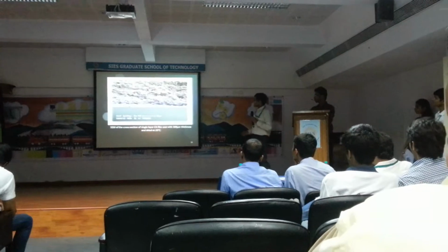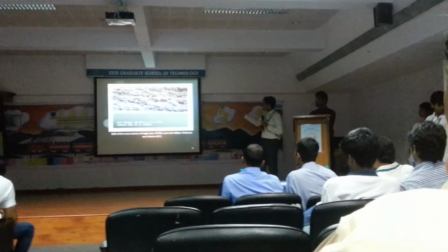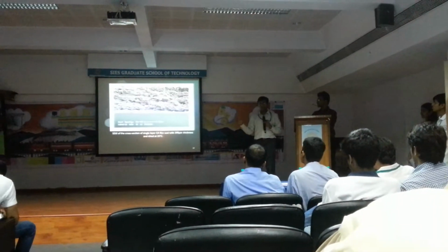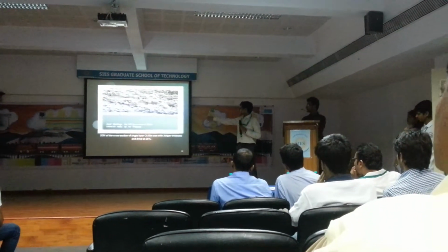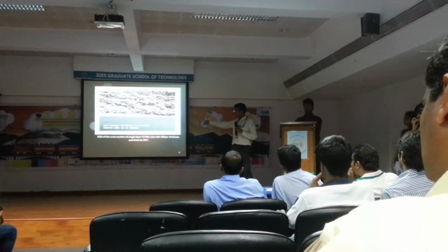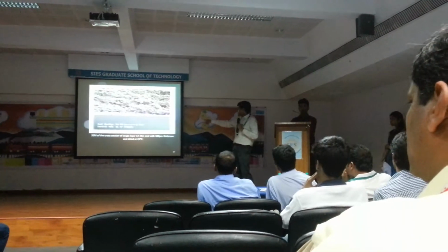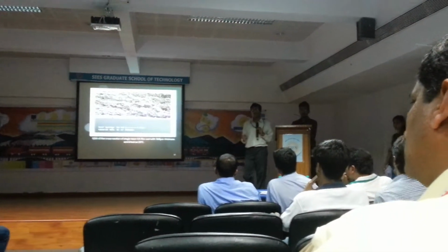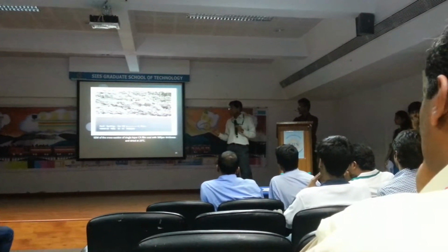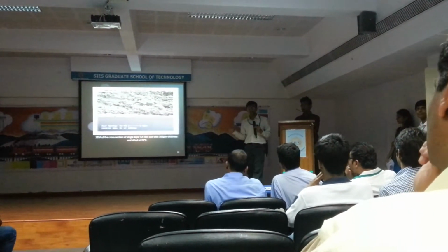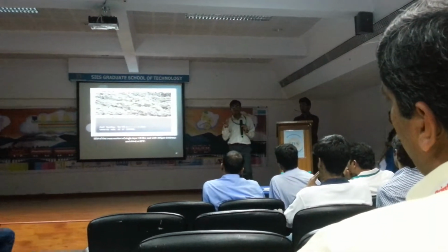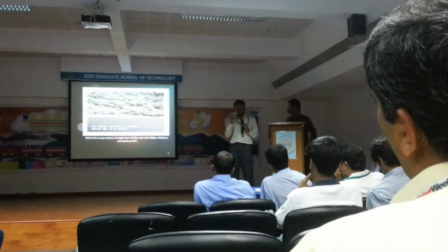This is actually an antimicrobial agent base layer. On this, the antimicrobial agent is applied. This is actually a 300 micron thick layer of cellulose acetate, which is made in such a way that the amount of monomers induced inside the layer is more than in normal cellulose acetate films, because this causes the porosity of the layers to reduce.